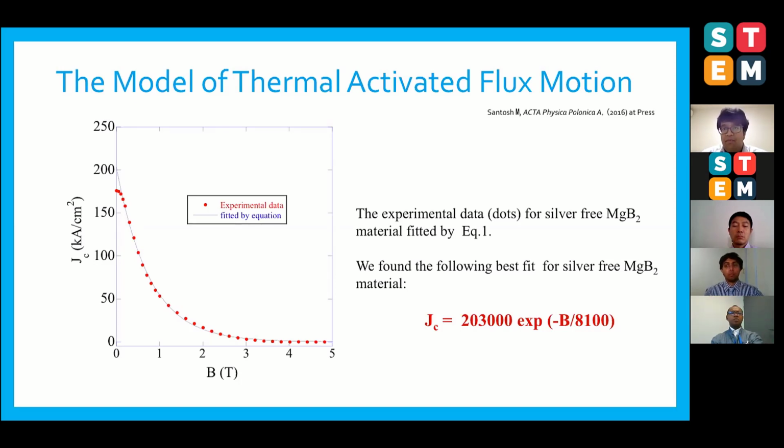But while creating these models, there were certain parameters which have to be kept in mind, because we need to take into account that the coherence length and the vortex core size in MgB2 are 20 times larger than compared to cuprates. So it means that the relevant defects will be much larger, whereas in cuprates they can be regarded as point-like defects, which are responsible for the secondary peak. Another point I wanted to point out from this graph is that in MgB2, only large defects are really effective, and these are known to contribute to the central maximum.